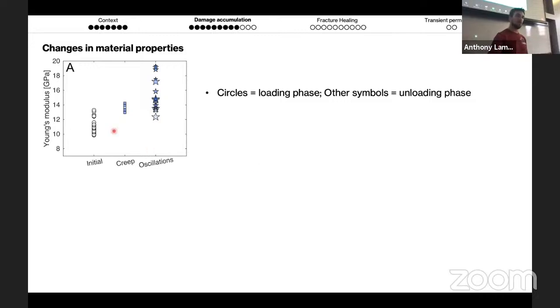So when I looked at the Young's modulus, the initial one is from the loading phase, and for these, it's during the unloading phase. What's quite weird is that if I introduce damage in a rock, the Young's modulus should be going down. That's pretty much what we see in every literature. Here, it goes up. So am I actually doing any damage to these rocks?